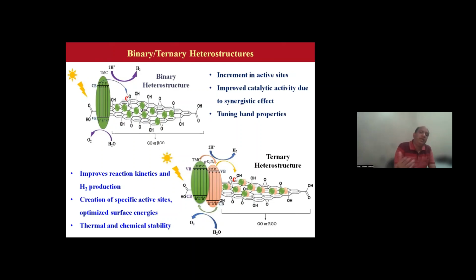Now, with the help of these components, you can make the binary or the ternary heterostructure. During the formation of the binary or ternary heterostructure, there is an increment in the active sites, and there is tuning of the band structure or band properties, so that they can improve their catalytic active sites due to synergistic effect, and there is improvement in the kinetics, so that it can give high hydrogen production.